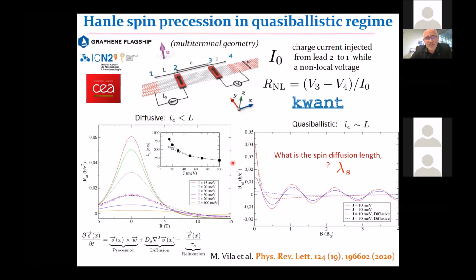We developed a methodology at ICN2 together with CEA, and we were able to make the first simulation of the non-local transport characteristics, especially here with an external magnetic field, the so-called Hanle spin precession, and we were able to investigate the transition from a dirty sample to a super clean sample where the electronic mean free path is much larger than the channel length, for instance. So we made a lot of progress, and this will probably help the interpretation of future Hanle spin precession measurements in ballistic devices.